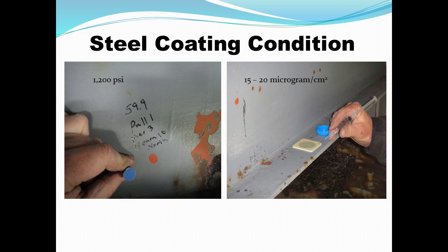As you can see here, we did some pulls. This is an example of one. They weren't all 1,200 PSI, but they were in that range, 1,000, 1,300, 1,400 PSI pulls. And we did a number of field chloride tests, and it ranged from 15 to 20 micrograms per square centimeter, which is pretty good. Of course, this was done in late April, early May, and it had washed off quite a bit by then.